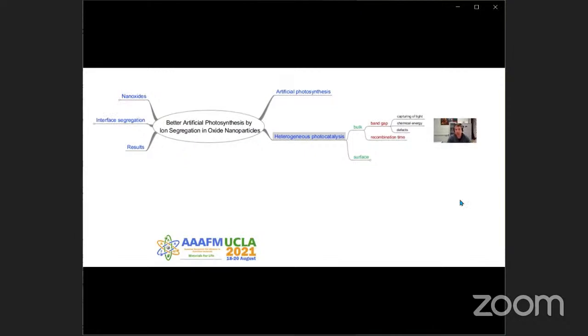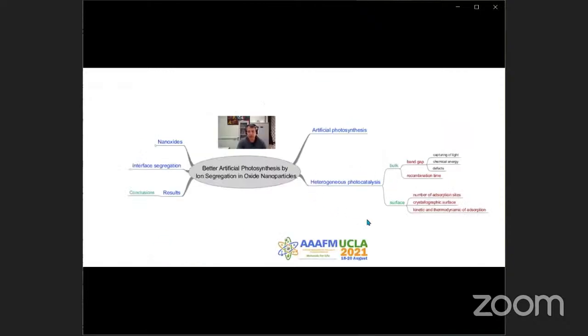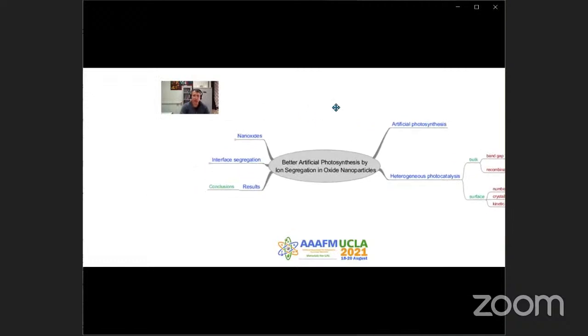Simultaneously to the bulk properties, the surface properties are very important for heterogeneous catalysis. And the surface determines the number of adsorption sites. This number of adsorption sites depends on the crystallographic surface and the kind of surface you have, and the kinetics and thermodynamics of adsorption, because all reactions depend on adsorption of species on the surface. To increase the photocatalysis, we need then a lot of surface, and then we work with nano-oxides.